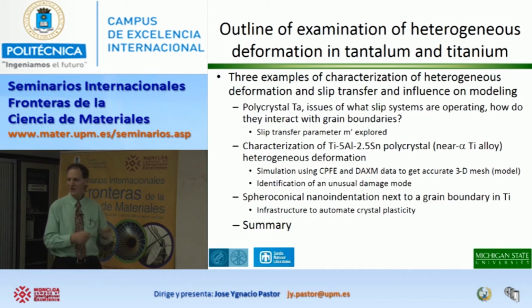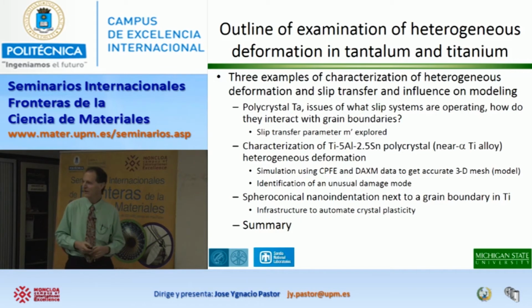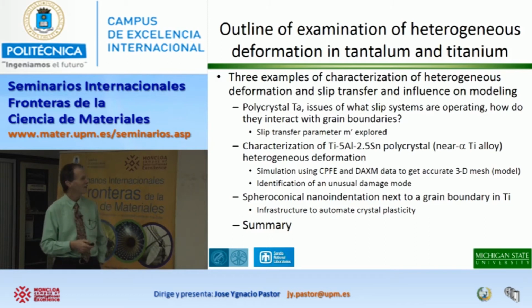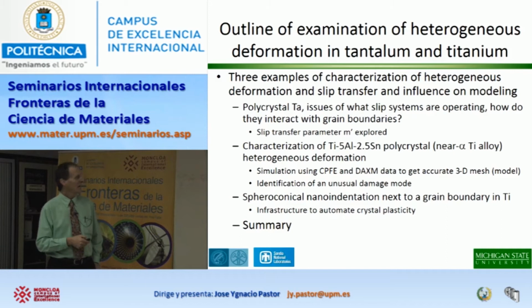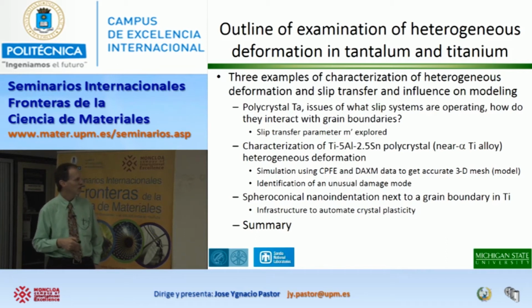Because it turns out that this fracture initiation parameter I showed you didn't really work in the titanium. And I haven't even tried it in the tantalum, because I just don't get cracks there. It just deforms a lot. OK. So we're going to look at a slip transfer parameter here, one that I will call M prime, which I'll describe to you, and then also look at some titanium samples in finer and finer detail.